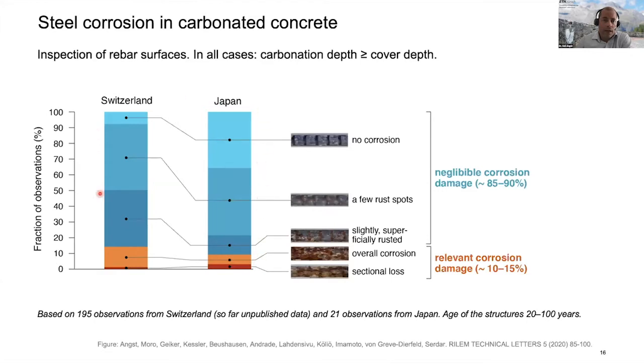In fact, all those blue areas here represent negligible corrosion damage, and only in about 10 to 15% of the inspected structures did we see relevant corrosion damage. So although the steel had been in carbonated concrete, in all these cases, there was not really relevant corrosion damage in the majority of cases.